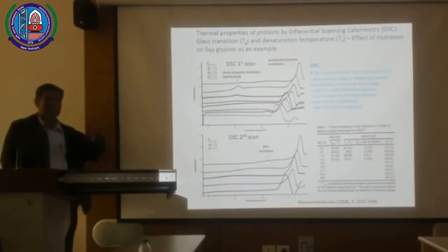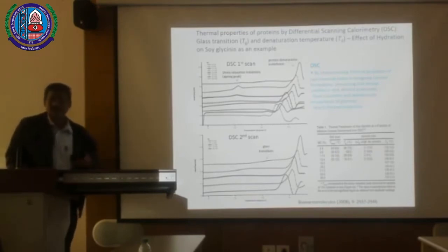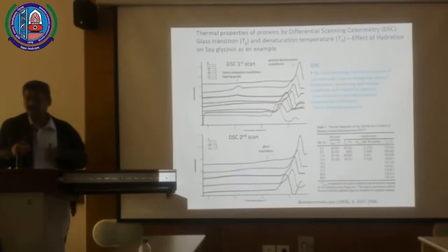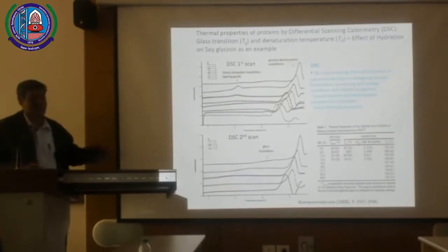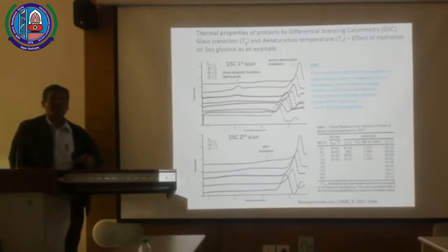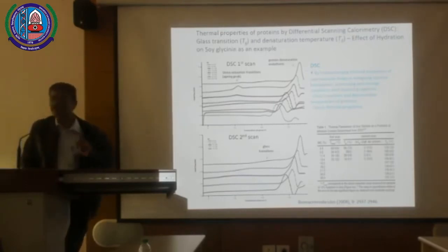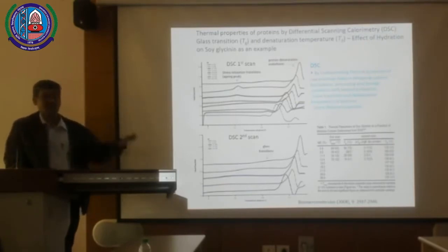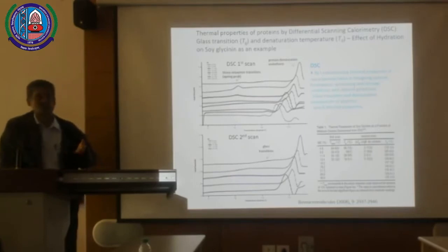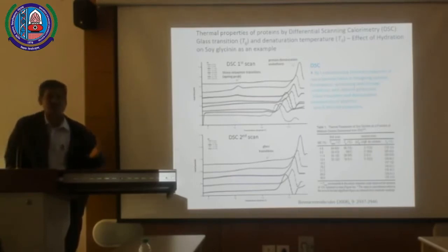Because this structure is changing from beta sheet to beta strand, it means that a structural realignment is occurring, a transition is taking place at that moisture. So please remember this 13% moisture here. I think this is the take-home message: if you are dealing with any powder, if the moisture content is above 11-12%, your protein conformation is different. It's no longer the native configuration. That's a clear answer. So that's experiment 2.